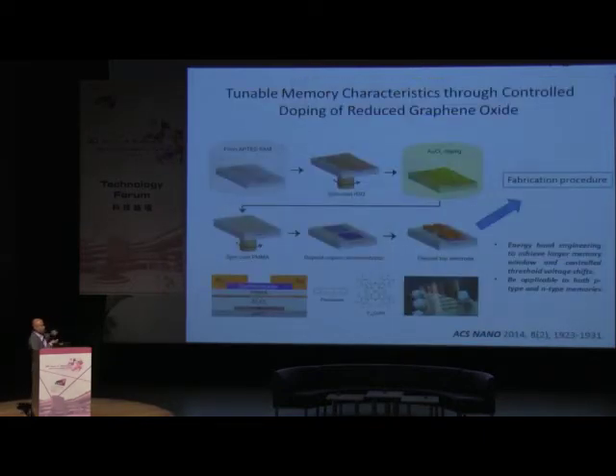Now, instead of making this layer by layer, can we make devices by putting everything together in one layer? So what we did is, we take a reduced graphene oxide and dope it with different metal chlorides. With gold, we moved the work function up by 0.5 eV. In fact, you can do it with platinum, palladium, and we found recently you can go up to 1 eV shift in the work function of the whole layer.